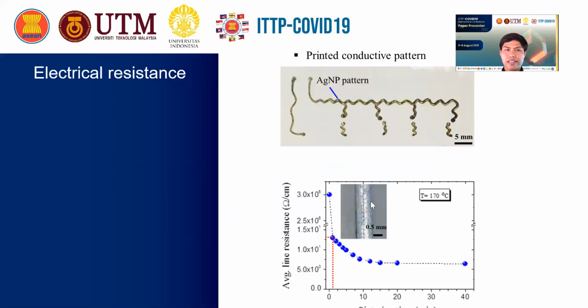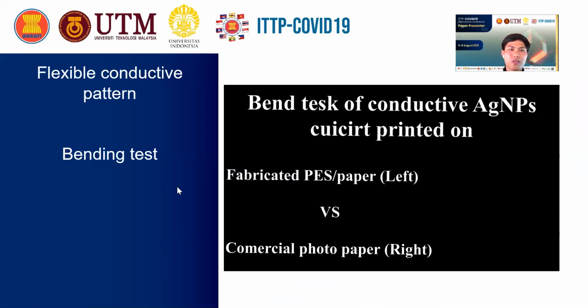So we test electrical resistance to confirm that the printed pattern remains conductive after annealing at high temperature to remove solvent and surfactant. When we anneal at 170 degrees, just 10 minutes is enough to provide the minimum electrical resistance in highly electroconductive patterns. And for flexibility, we provide some tests comparing the PES and simple paper.